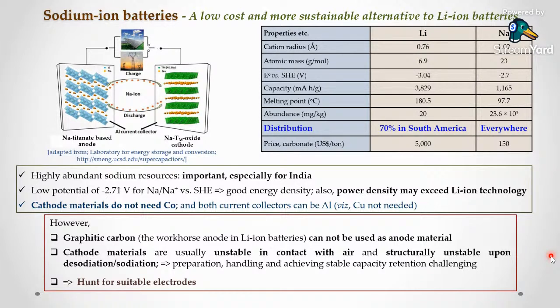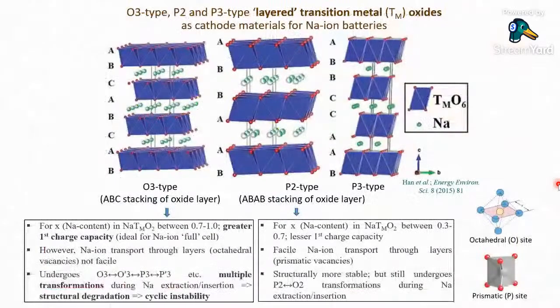Cathode materials, again, the layered transition metal oxides, structurally they can be stable during the initial stages, but they are highly unstable upon exposure to air and water, which can deteriorate the structure in a matter of even minutes, as we have seen. They are highly hygroscopic that way, and upon electrochemical cycling, upon removal and insertion, they undergo a lot of phase transformation changes, which also degrade the material and hence the capacity of the cathode material. So these aspects need to be addressed, and today I will focus on the second part, that is the cathode materials, and show one example.